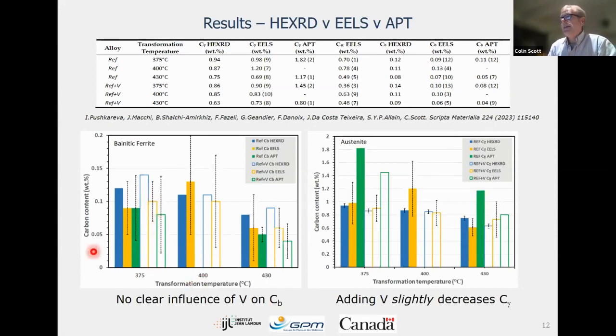We can't see any clear influence of vanadium on the amount of carbon that we measure in the bainite. We don't see any real difference at all. These error bars here, this is not measurement error. This is the actual dispersion in the data. So this is showing you that these values are quite dispersed. In other words, the carbon content in bainite is not uniform. It varies from lath to lath, and it varies by quite a lot.